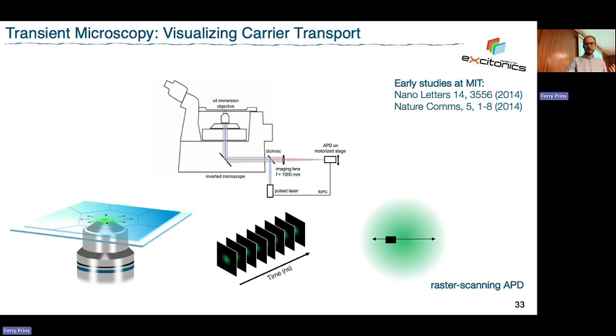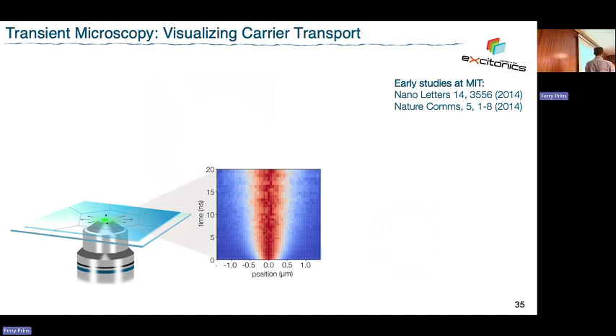Now, instead of taking an entire movie, if you have a material that's isotropic, everything moves in the same direction and same speed, then you can reduce your acquisition time. You just take a single slice through your population. So at time 0, we have our 250 nanometer original population, and then as time goes by, we see the population broadening.